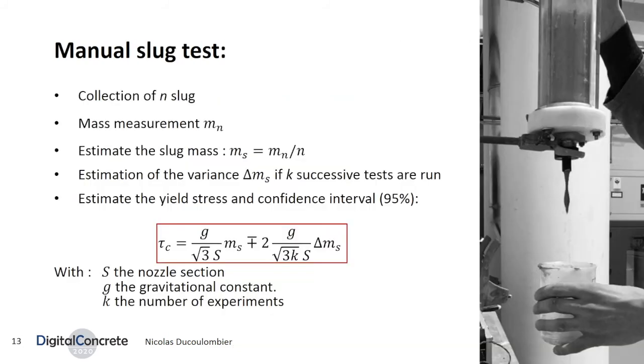The first one is a manual protocol that only requires, in addition to the extrusion device, a simple balance and a container. For the first part of the experimental validation, the specific extrusion device, shown on the right picture, is equipped with a 10 mm diameter nozzle and used together with the manual protocol presented here. Using the fundamental relation of the slug test, the yield stress assessment can be easily performed by the collection of a given number of slugs, followed by a simple mass measurement.